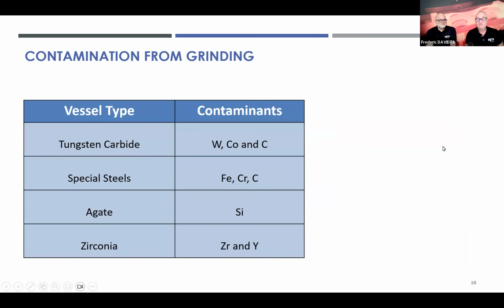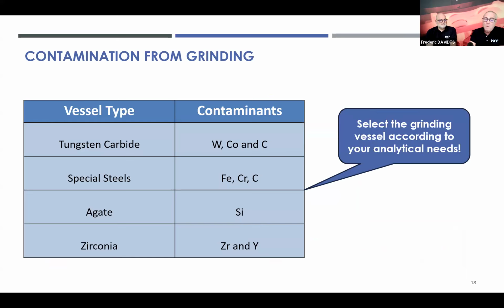There are different vessels available on the market, and depending on what your analytical needs are, you can select the vessel. If we take, for example, the tungsten carbide, which is generally used, we have to be aware that tungsten, cobalt, but also carbon will contaminate our sample. So we must be aware, if I want to analyze cobalt or tungsten in a geological sample, maybe it's not the best choice.